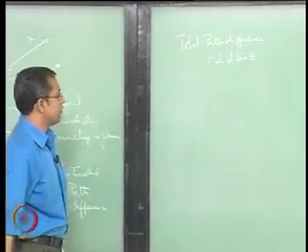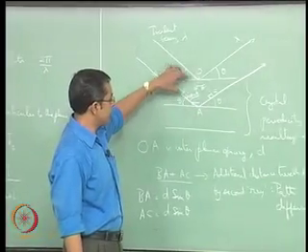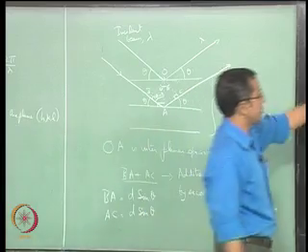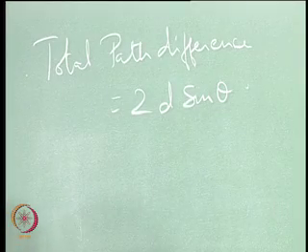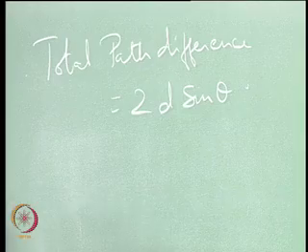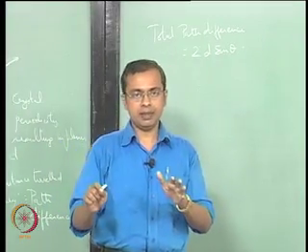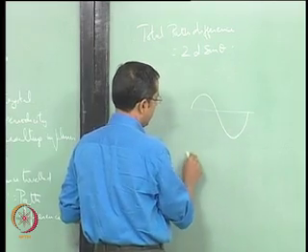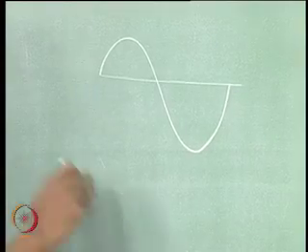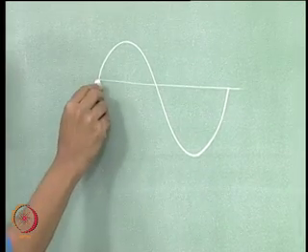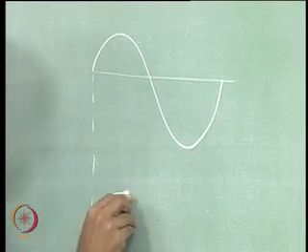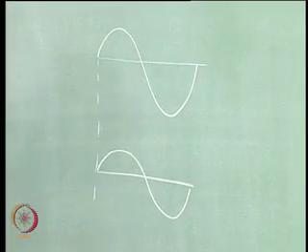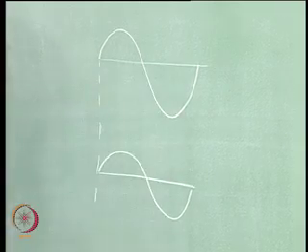Okay, so that is the total path difference between the two waves that have come to the adjacent planes and moved away from them. For constructive interference between those two waves that we are looking at, this path difference should be an integral multiple of the wavelength. Only then, so for example you have a wave like this, the wave from the adjacent plane could have travelled any amount of additional distance, but eventually when it comes to this point, it should once again come back the same way. Then these two are exactly in phase, there is constructive interference.